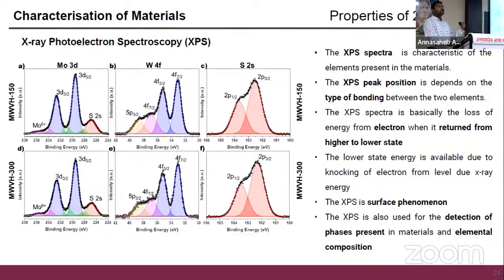XPS is also typically used to map the elemental composition. If we take the area under this curve and compare with each other, we can find the composition, such as the ratio between tungsten and sulfur, or molybdenum and sulfur. We can also find the vacancy, for example oxygen vacancy or sulfur vacancy, easily using this XPS technique by taking the area under the curve. There are some XPS concentration calculation formulas which you can use to find the concentration.